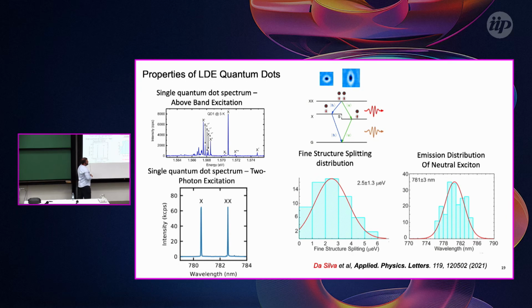Another advantage of these gallium arsenide quantum dots is that you can control the emission wavelength and make a very narrow emission distribution in wavelength. This is very nice, because if you want to find two quantum dots with the same optical properties, it's not as difficult as in the indium arsenide system.